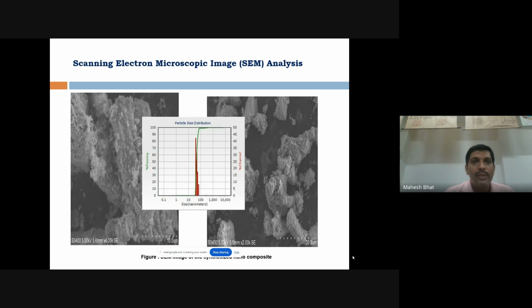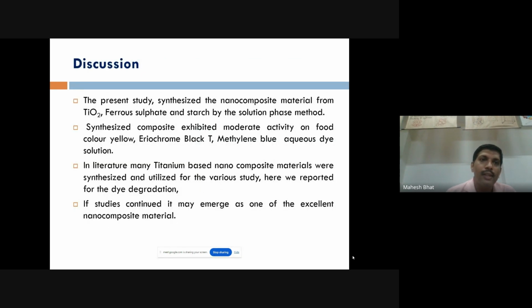This image shows the scanning electron microscopic image, and the particle size distribution was also determined by the DLS method, and it shows a particle size of around 100 nanometers. The present study synthesized the nanocomposite material from TiO2, ferrous sulphate and starch by the solution phase method. The synthesized composite exhibited moderate activity on the food color yellow, Eriochrome Black T, and methylene blue dyes in aqueous solutions.